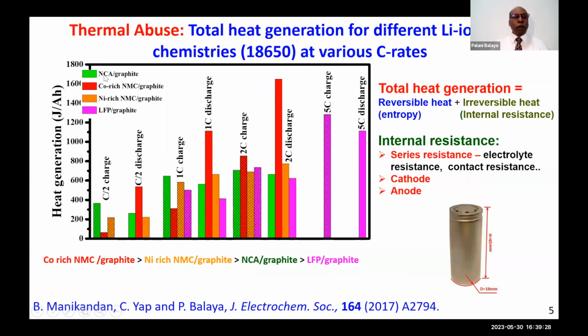So you can see here among the 4, at very low C rate, 2-hour charging, 2-hour discharging, LFP does not even release any heat at all. These are actually normalized, joule per ampere hour, normalized for different chemistries. So it doesn't even release any heat. So very, very safe. And if you go to very high C rate, for example, 5C charging, 5C discharging, that means in about 12 minutes charging, 12 minutes discharging. Again, you see that only LFP technology releases less heat.